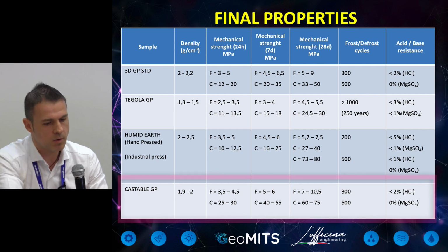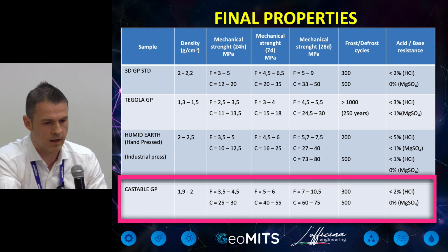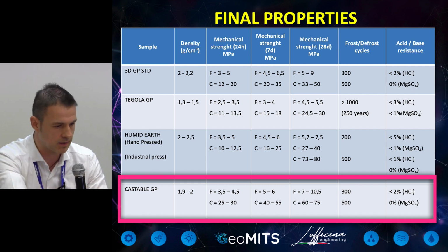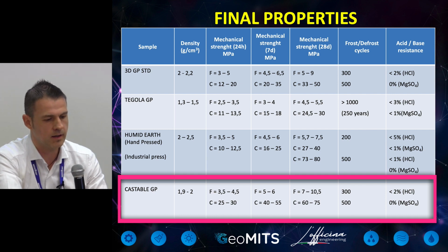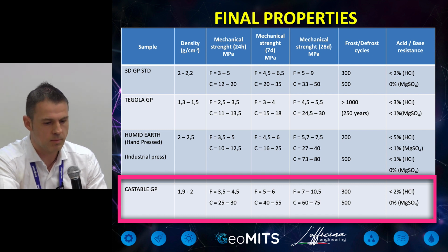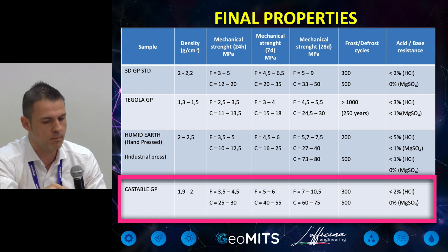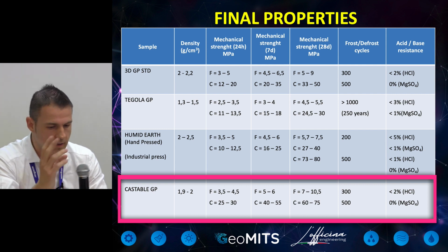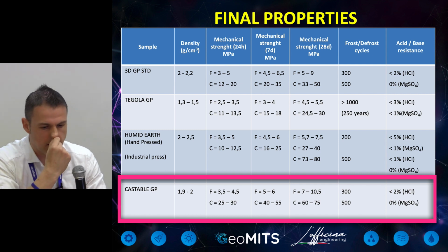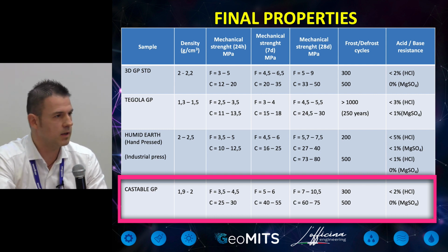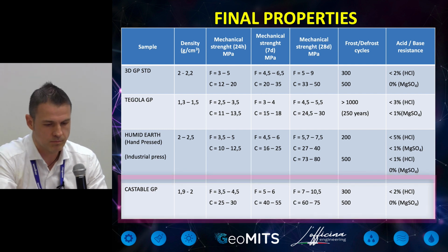And the castable has an average of other consistency, so it is more fluid, not like roof tiles, and quite isotropic, not like a 3D mortar. And I obtained a very interesting result. And depending on the size and the granulometry, it's possible to rise up to more than 10 MPa about flexural strength, and about 75 or 80, depends, about compressive strength, with good stability in acid or basic medium.